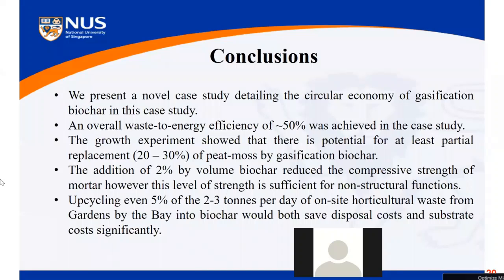So next, we would like to show the conclusion of the study. Basically, we have presented a novel case study dealing with the circular economy of gasification biochar. We have found that an overall waste to energy efficiency of about 50% was achieved in this case study. The growth experiment showed that there is potential for at least partial replacement, about 20 to 30%, of the peat moss by gasification biochar.